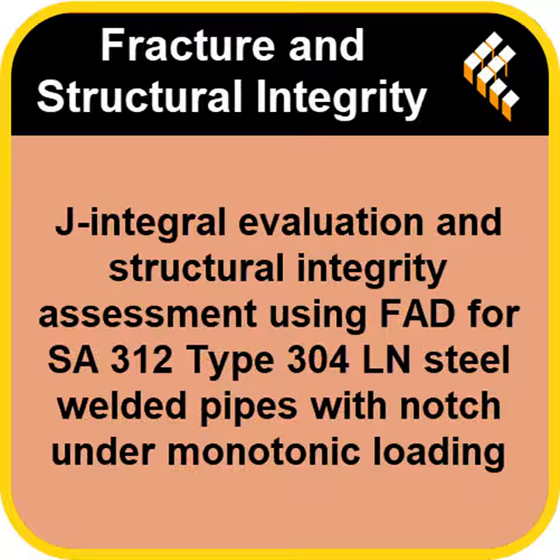Okay, so the verdict seems simple then. You calculate your specific assessment point, that LR, KR coordinate pair. If that point lies inside the failure assessment line on the diagram, the flaw is acceptable. The crack is considered stable under that load. Correct. But if it lands above or outside that line, the structure is predicted to fail. Instantly, potentially. That's the prediction, yes. Unstable. And landing exactly on the line. That means you are at the critical condition, essentially zero safety margin left. It's the boundary. Right on the edge.